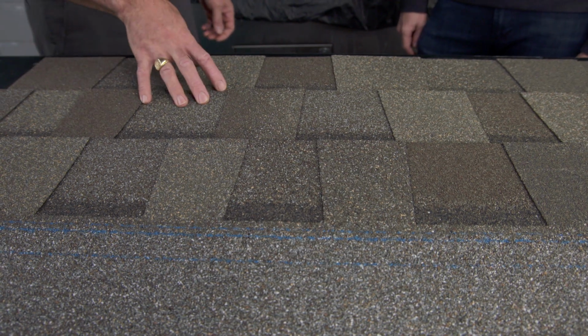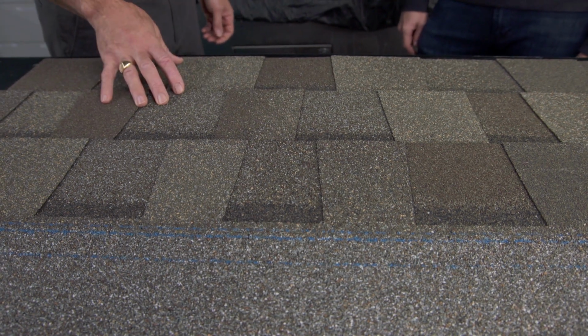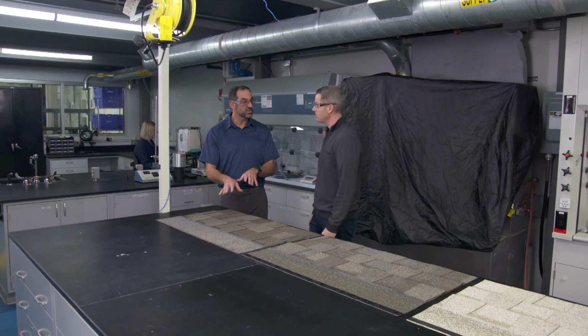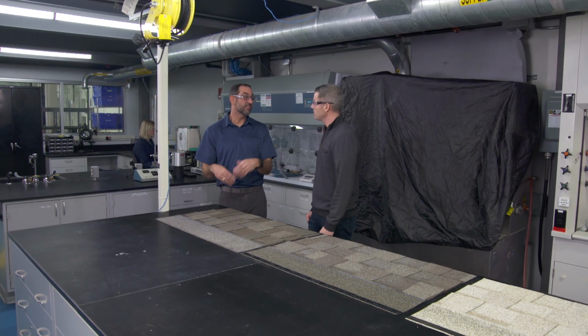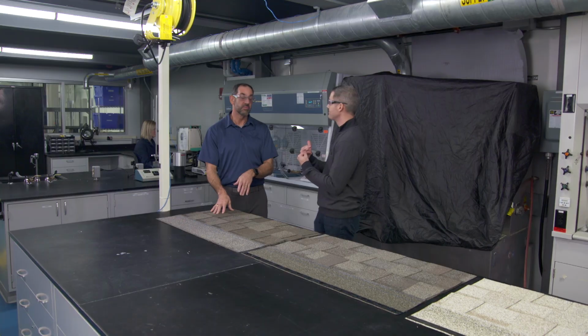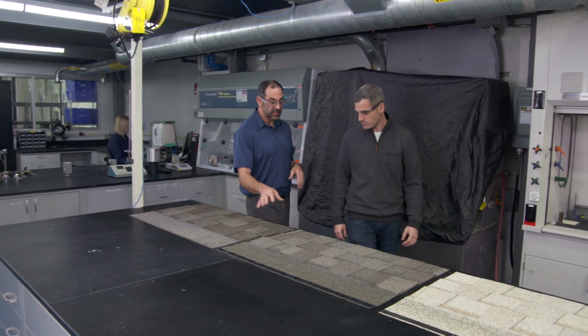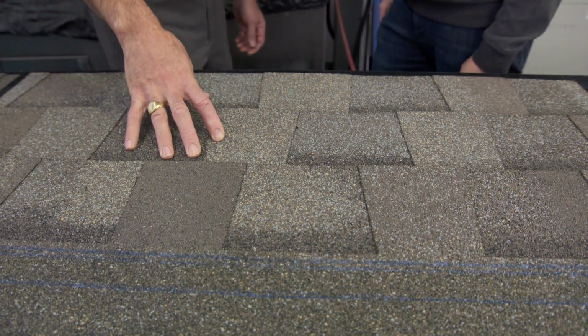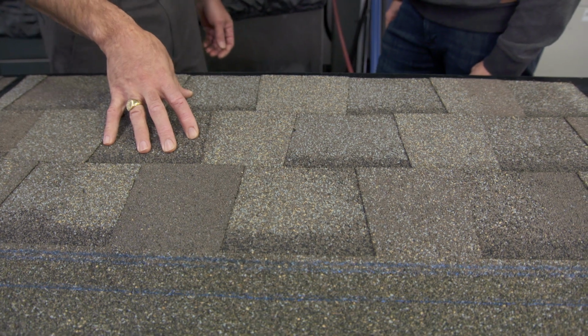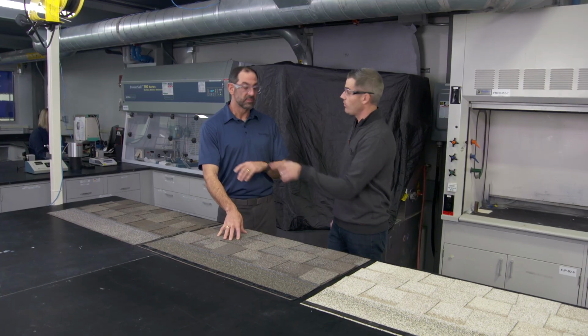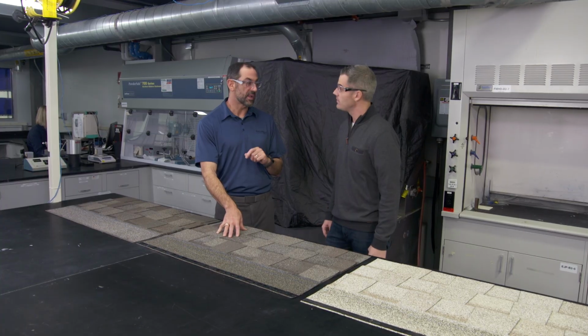Correct. When you look at a standard shingle, this has a solar reflectivity of around 8 to 10%. Pretty standard for a dark material. A black shingle can have around 3 to 5% solar reflectivity. It's really low. Very low. When you design solar reflective shingles, we design these to have a solar reflectivity of about 20%. So more than double that. Yes, more than double has a dramatic impact on your roof.